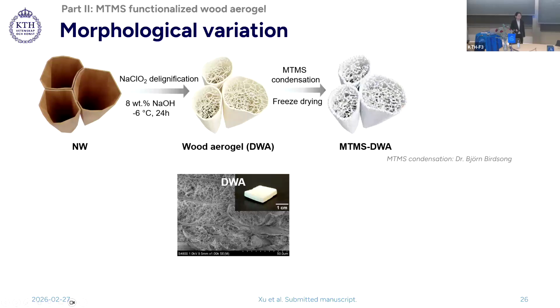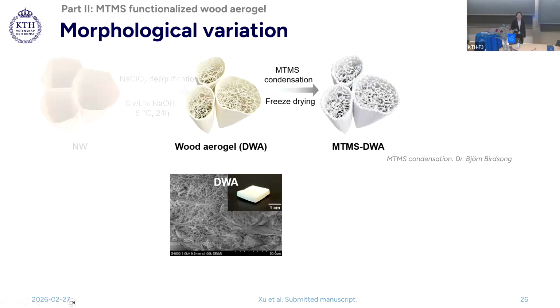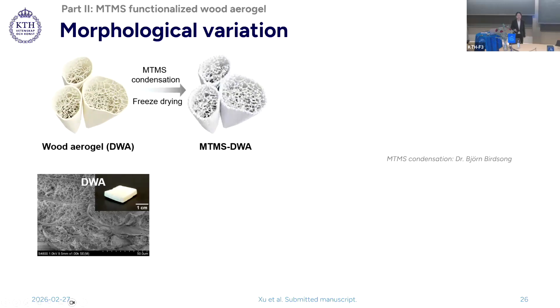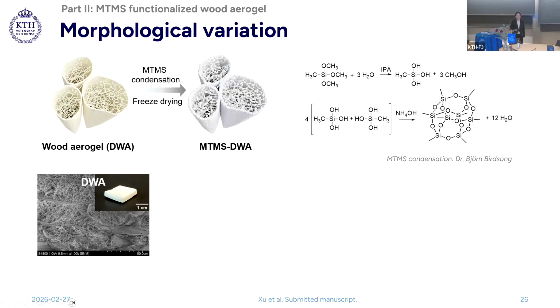MTMS condensation was then performed to create a hydrophobic network in order to address the inherent moisture sensitivity of cellulosic material. MTMS was selected as a sealing precursor due to the presence of methyl groups on the final silicon structure.